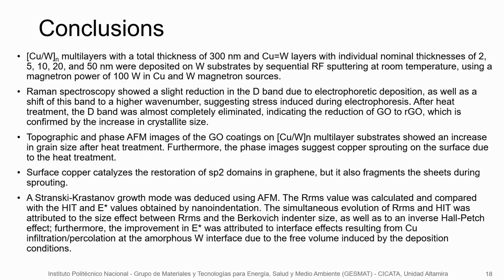So this can be related to the differences and the dispersions in the hardness and the reduced elastic modulus obtained by nanoindentation. The simultaneous evolution of the roughness and the hardness was attributed to the size effects of the hardness and the Berkovich indenter, as well as an inverse Hall-Petch effect. Furthermore, the improvement of the elastic modulus was attributed to the interface effect resulting from copper infiltration and percolation at the amorphous tungsten interface due to the free volume induced by the deposition conditions.